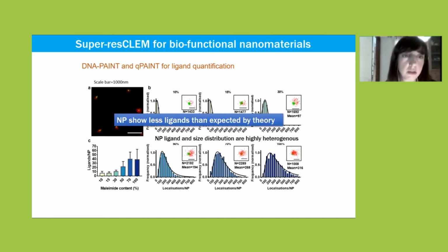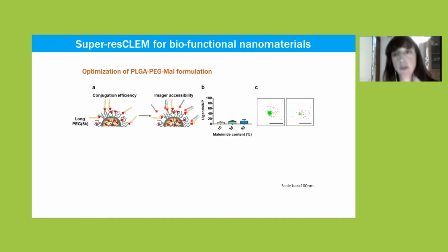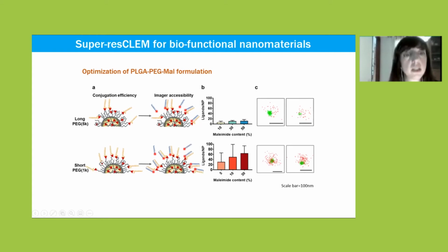Okay, so this method was really good for us because we could learn, and this is a technicality, but it's really important. Seeing the results, what we could do is go back to our formulation and change it in order to have more ligands exposed on the surface of the nanoparticle. So if this was the formulation that I showed you before, what we did is to change it and have a short PEG. I will explain now.